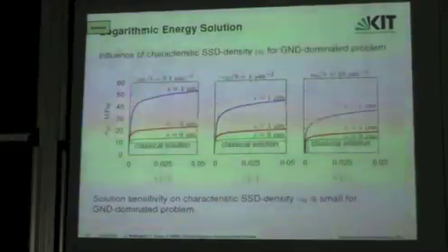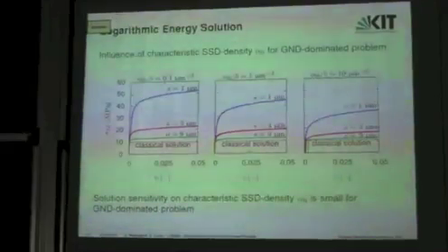And this is a very interesting result because we just introduced the blue curve for regularization reasons, but we also find a very nice physical interpretation for this regularization. Okay. Now, as I said, there's only one free parameter of your energy, that's the SSD density, which you have to guess. And this is usually a bit complicated because one might be lucky if you have a rough idea of the order of magnitude of your SSD density.